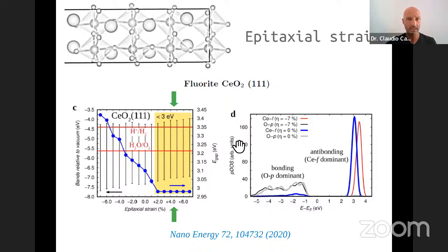So we found that, in this plot, I represent the energy band gap, which is on this axis here, and how it changes with epitaxial strain. And on this other y-axis, we have the band alignments, right? So this is the top of the valence band, and this is the bottom of the conduction band. How do they change as a function of epitaxial strain, right? Where here we have the HER and OER potential energies, right? So for the energy band gap, there is a strong effect induced by epitaxial strain. Later on, I will explain very briefly what the fundamental causes of this are, right? But this is something that had been done before, was known. What we were looking at was how these band alignments were changing at the same time, right?